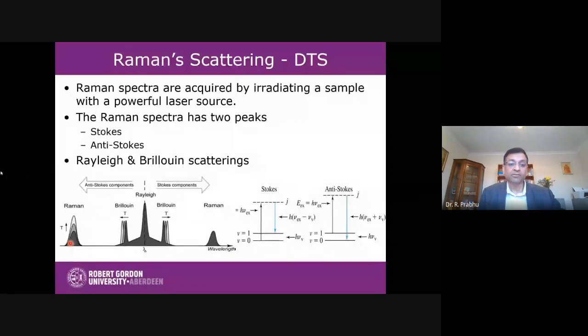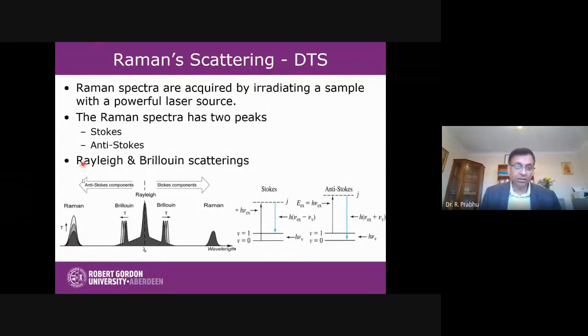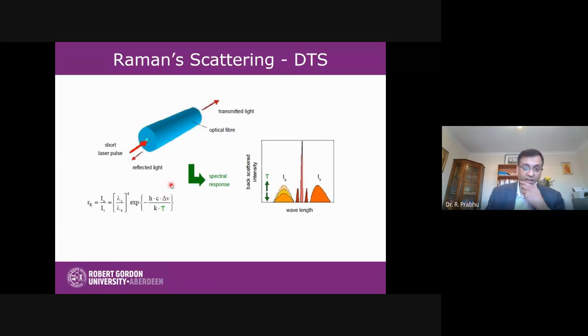So you have anti-Stokes, which is temperature sensitive, and a change in intensity of this anti-Stokes line can be correlated to temperature variation. And in this case, the Stokes can work as a reference signal. So the ratio of these two can be used for monitoring temperature variations along the fiber. In this case, you see the optical fiber sending a light pulse and getting back the backscattered light, and these are the two Raman signals.